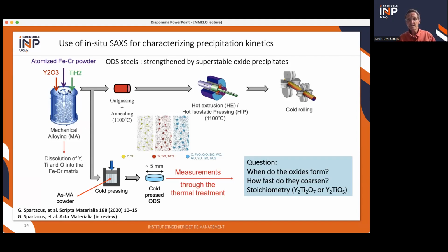And after that, the process goes to annealing and then hot extrusion or hot isostatic pressing. And it's during these steps of annealing and hot deformation that you form these precipitates. But really, it's very difficult to characterize when this happens. What is the kinetics? Do you have any coarsening of these particles? And what is the stoichiometry of these very, very small particles? There is always a debate between two different phases, the pyrochlore phase and the Y2TiO5 phase.